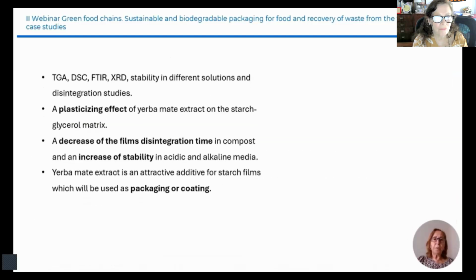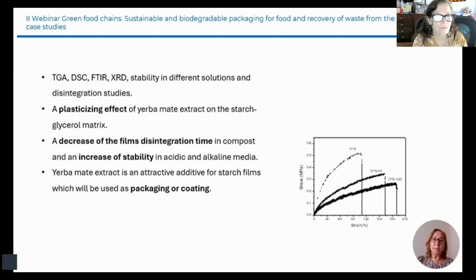We developed thermal analysis, and structural and chemical analysis also. We studied the stability in different solutions and the disintegration behavior. We found a plasticizing effect of yerba mate extract on the starch-glycerol films, as you can observe in the stress-strain curves on the right.